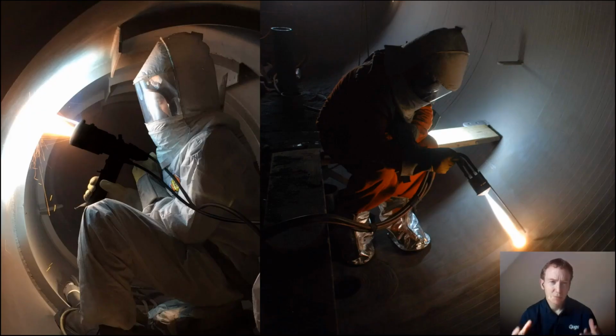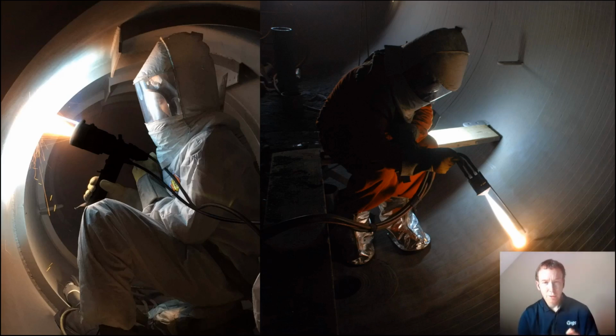So let's look at some examples of case histories of thermal spray applications in the field. In the pictures you can see here on the left-hand side, we're applying a thermal spray, a high-velocity thermal spray barrier with a twin-wire arc system. On the right-hand side, there's an HVOF system. Both systems are high velocity. Both systems create a dense microstructure. High-velocity arc spray on the left is the more common system used because it's more robust. It applies a wider range of materials and is more suitable for field application.